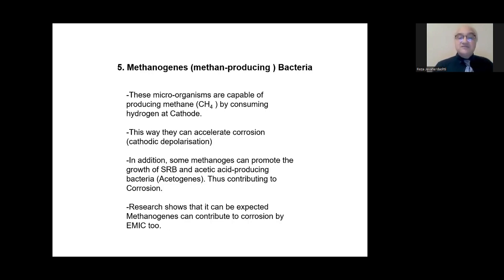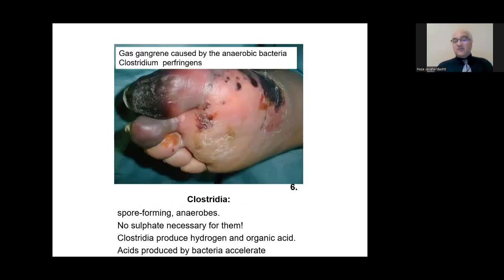It is interesting to see item number 3. Some methanogens can promote the growth of SRB and acetic acid producing bacteria. And then you can see they are contributing to corrosion. Clostridia are not only important in the literature of corrosion, but they have been known for contributing to gangrene, for example, as you can see here, and they produce ample amount of hydrogen, resulting in hydrogen-induced cracking, as well as producing acids that will lower pH.